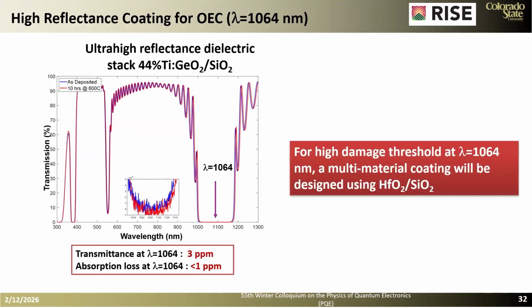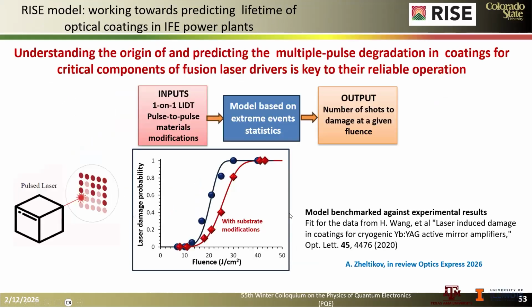These are some of the coatings that we developed for 1064 nanometers, designed on hafnia silica, and we obtained very high reflectivity, a transmittance of 3 parts per million, and a very low absorption loss of the order of 1 part per million. We're also working in collaboration with Texas A&M, who are also members of the hub, to develop ways to predict the multi-pulse degradation that coatings experience in fusion laser drivers.